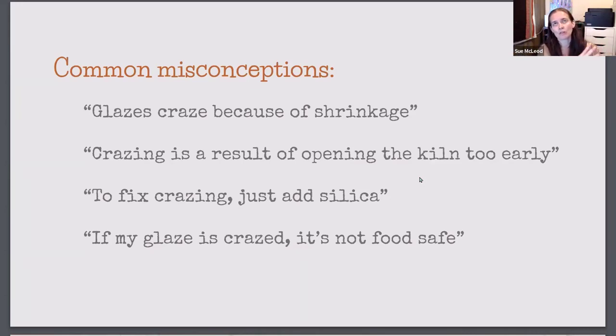So a lot of people say, oh, you opened your kiln too early. Your kiln was too hot when you opened it. That's why your glazes are crazing. That's not actually the case. If a clay body and a glaze don't have a thermal expansion match, then the glaze will craze regardless of how slowly it is cooled and what temperature you open the kiln at.